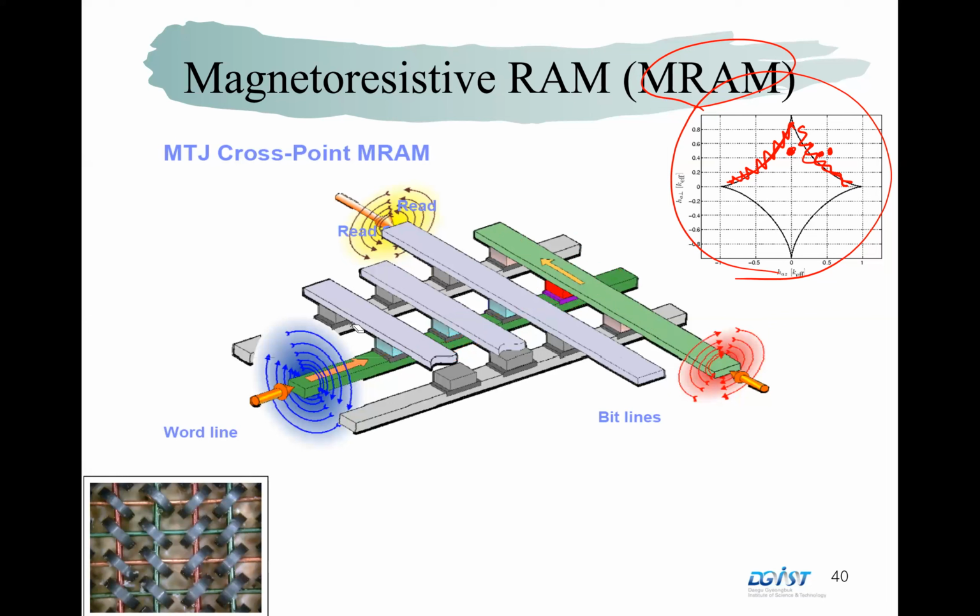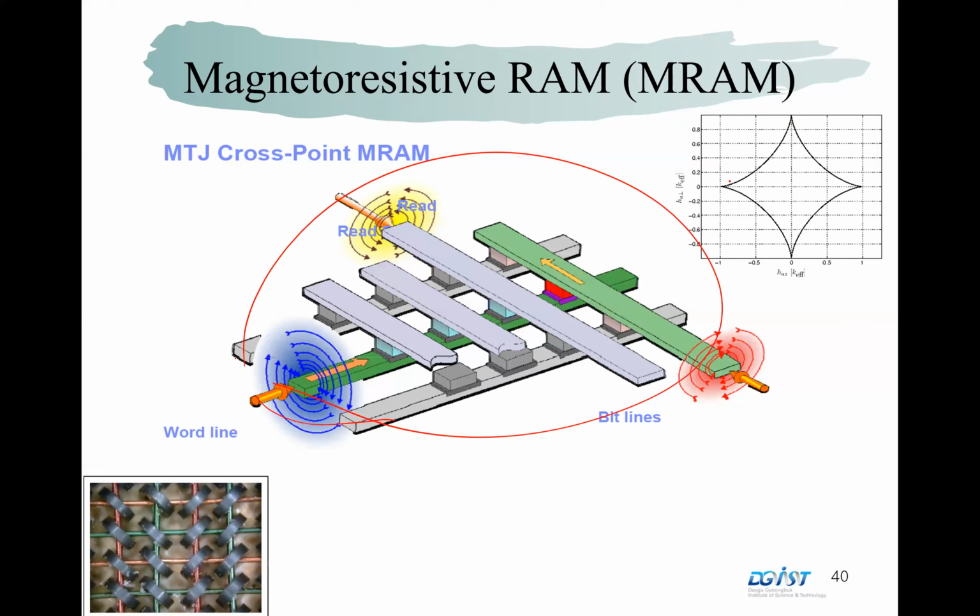Okay. This kind of problem is solved by a new technique called spin transfer torque. But still, the idea of switching with the magnetic field is very important in many applications. So understanding the Stoner-Wohlfarth model is very useful for real research. If you include more energy terms in the Stoner-Wohlfarth model, for example, exchange coupling or exchange energy, or higher order uniaxial anisotropy energy, the basic physics is the same. The only difference is in the numerical details.